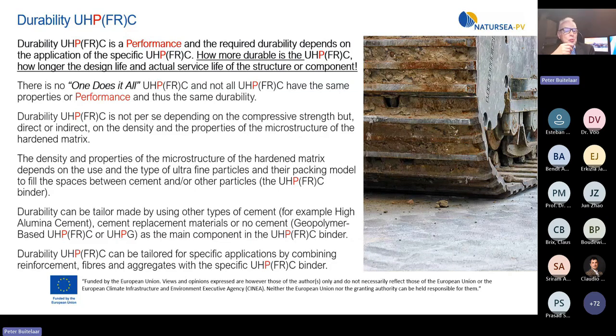Durability of UHPC is not per se dependent on the compressive strength, but directly or indirectly on the density and the properties of the microstructure of the hardened matrix. The density and properties of the microstructure of the hardened matrix depend on the use and type of ultrafine particles and the packing model to fill the spaces between the cement or other particles. We call this the binder. Durability can be tailored by using other types of cement, cement replacement materials, or no cement as the main component of the UHPC binder. Durability of UHPC can be tailored for specific applications by combining reinforcement fibers and aggregates with the specific UHPC binder.